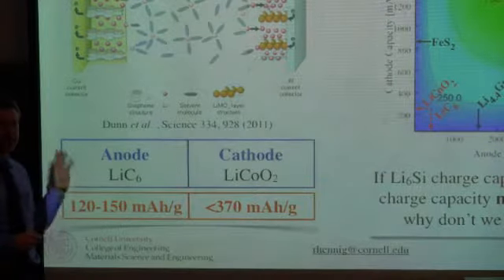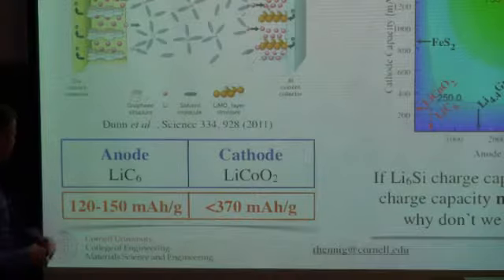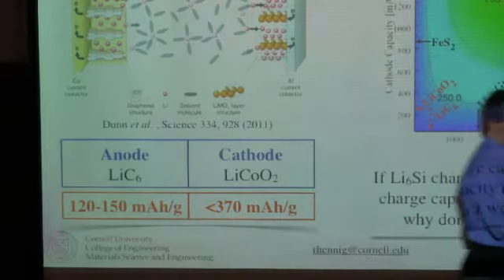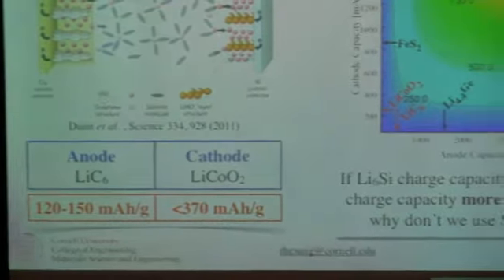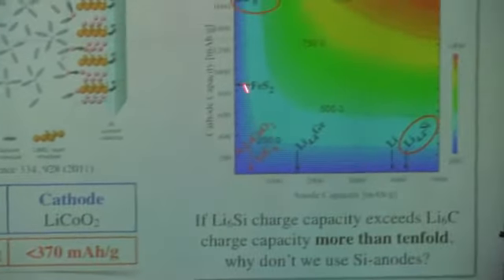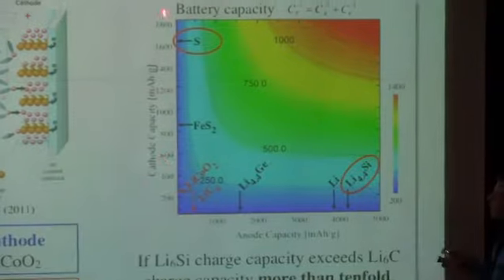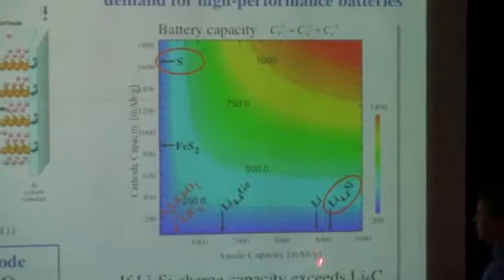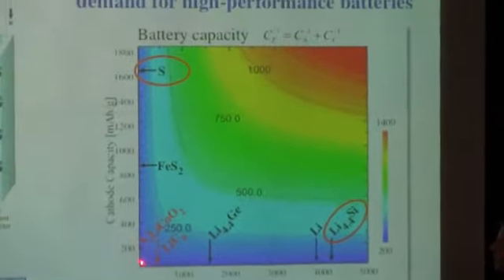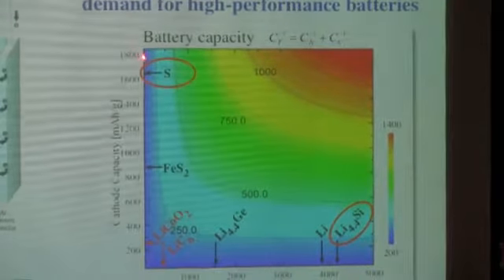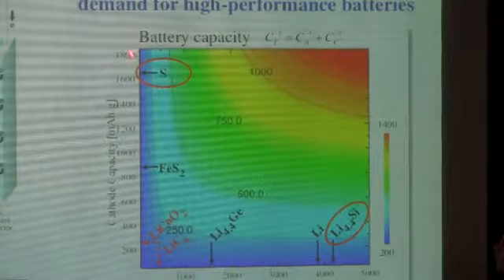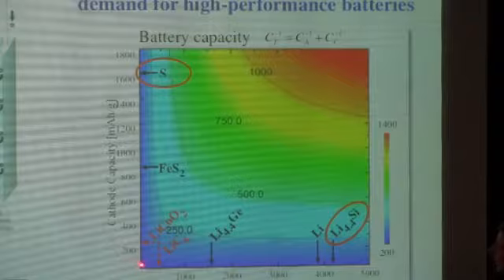So if you take a gram of that anode or cathode, you can store about 100 to 300, 400 milliamp hours per gram. So just to give you a ballpark number. On the second graph here, I'll show you for various cathode materials and for various anode materials what their capacity could be. The scale here you see immediately goes from 0 to 1800 milliamp hours per gram for the cathode, but for the anode we go all the way up to like 4,000 or 5,000 here.